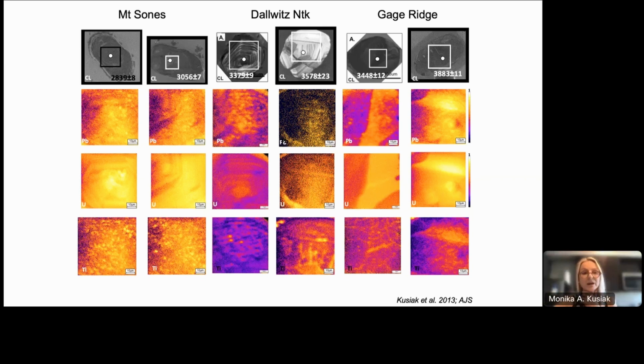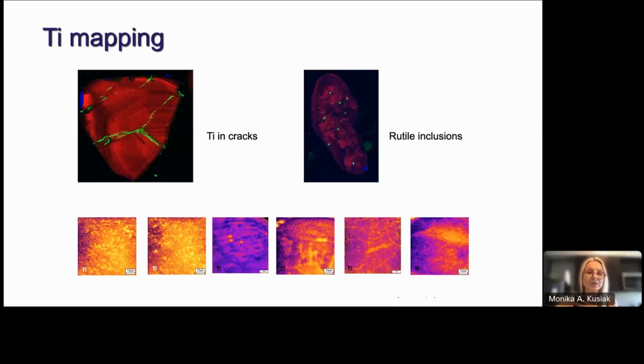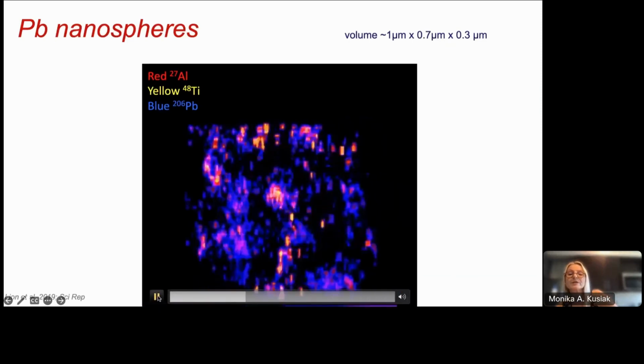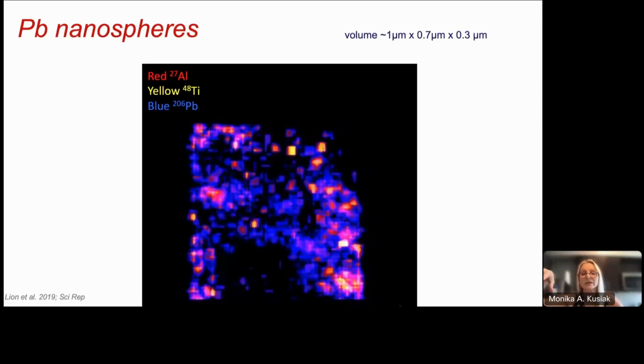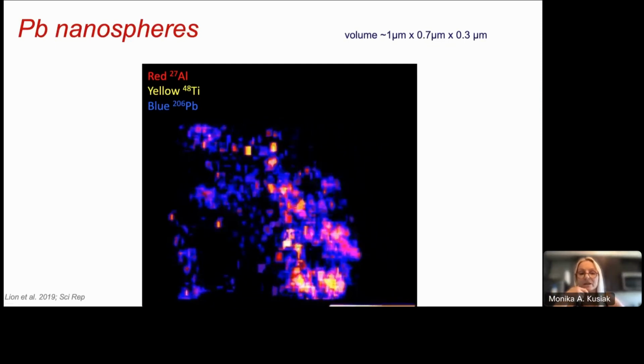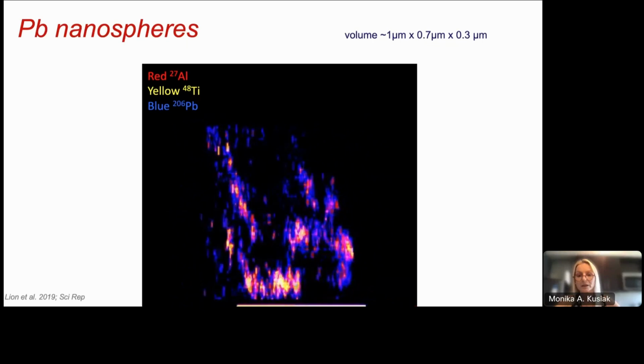And this was my Marie Curie project, later developed into the Humboldt project. So I started to work on this problem. I never really focused that much on titanium, because the lead problem is still not resolved. But I would like to show you just an example done on the synchrotron: if titanium is in the cracks, we can see how it is in the cracks. If it's an inclusion, we can see these are inclusions. But this is a really heterogeneous distribution of titanium. And as well, using the NanoSIMS, we made a kind of 3D mapping to see this. So we can see that next to titanium and lead, we also had aluminum in this zircon.